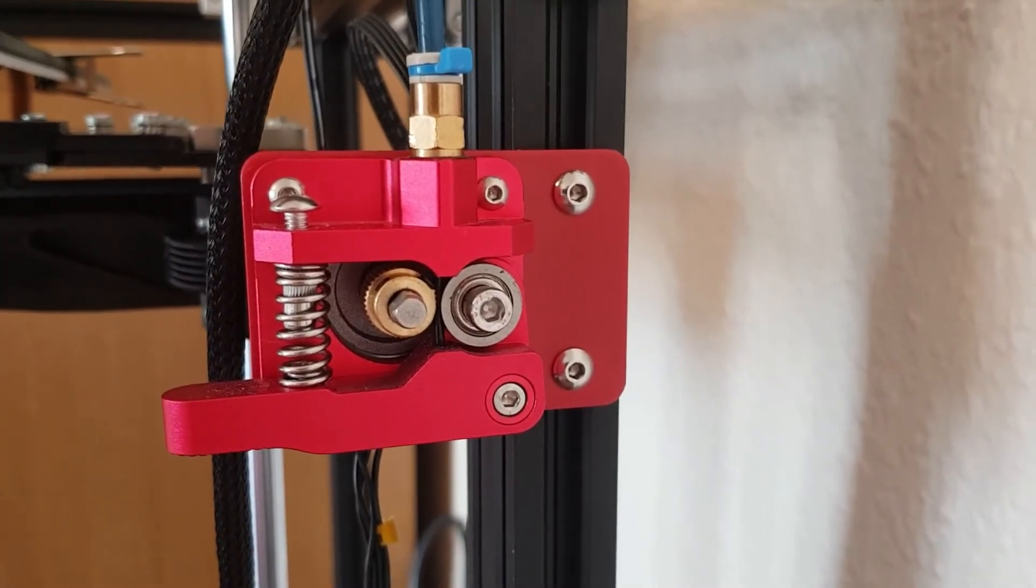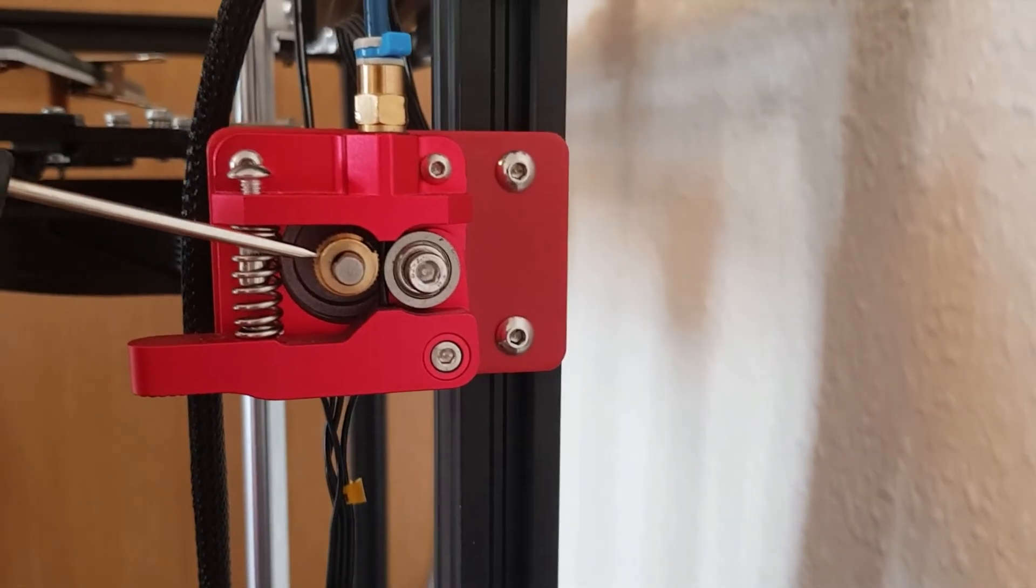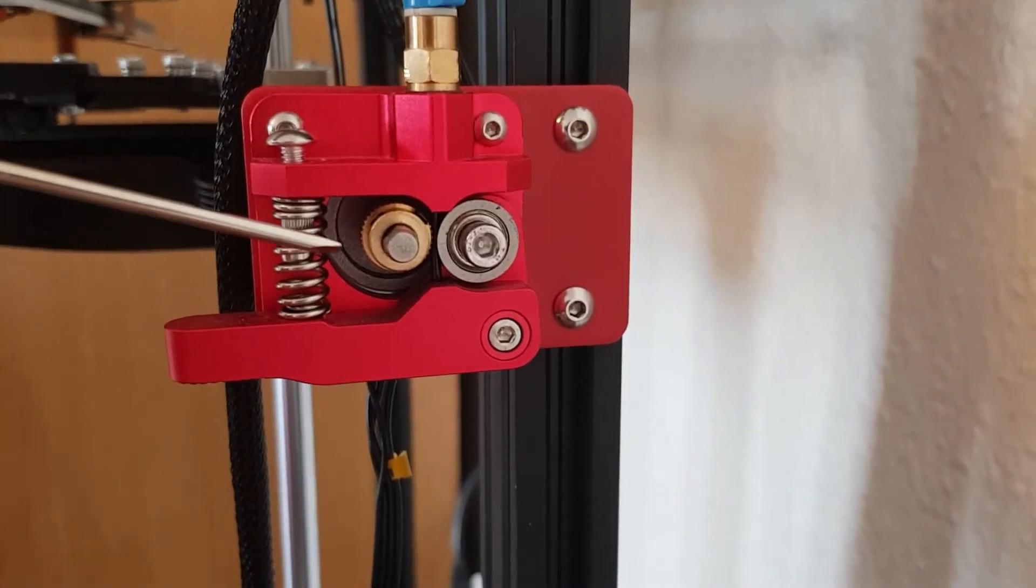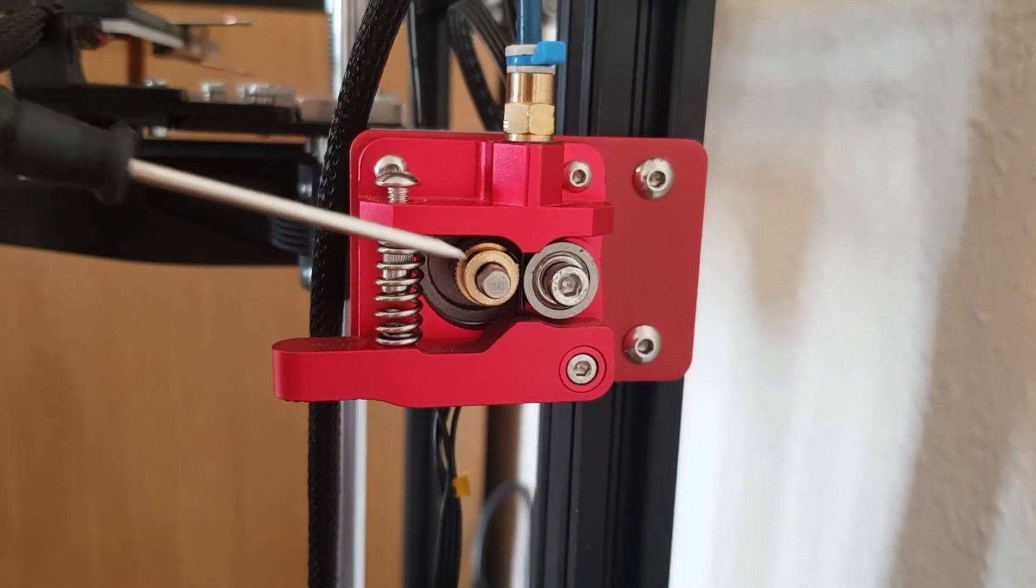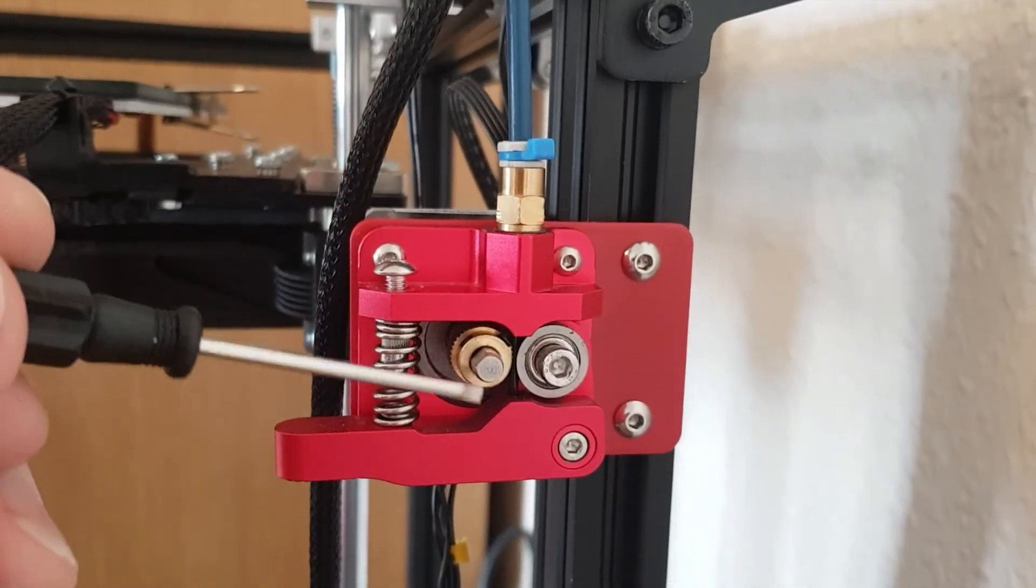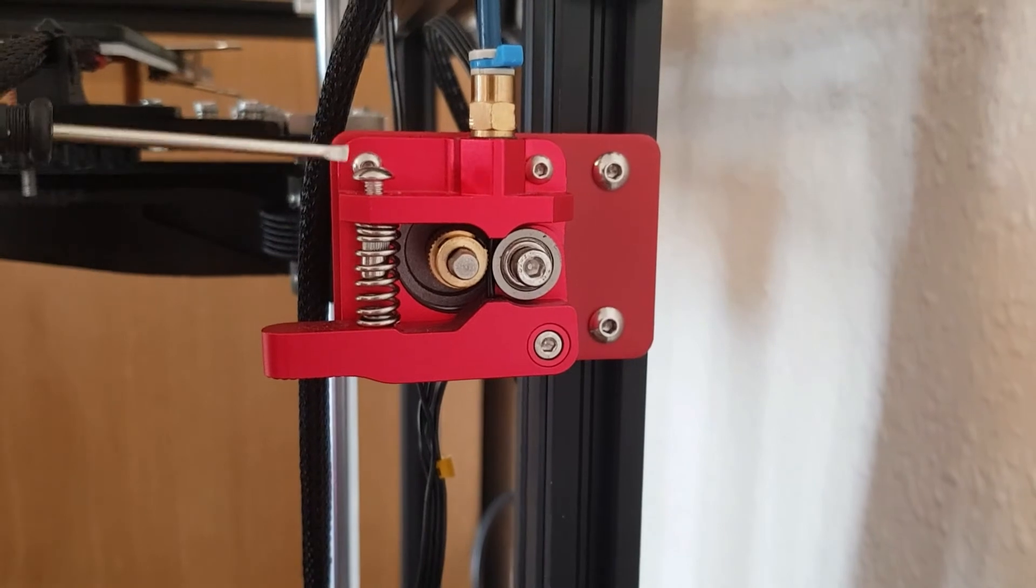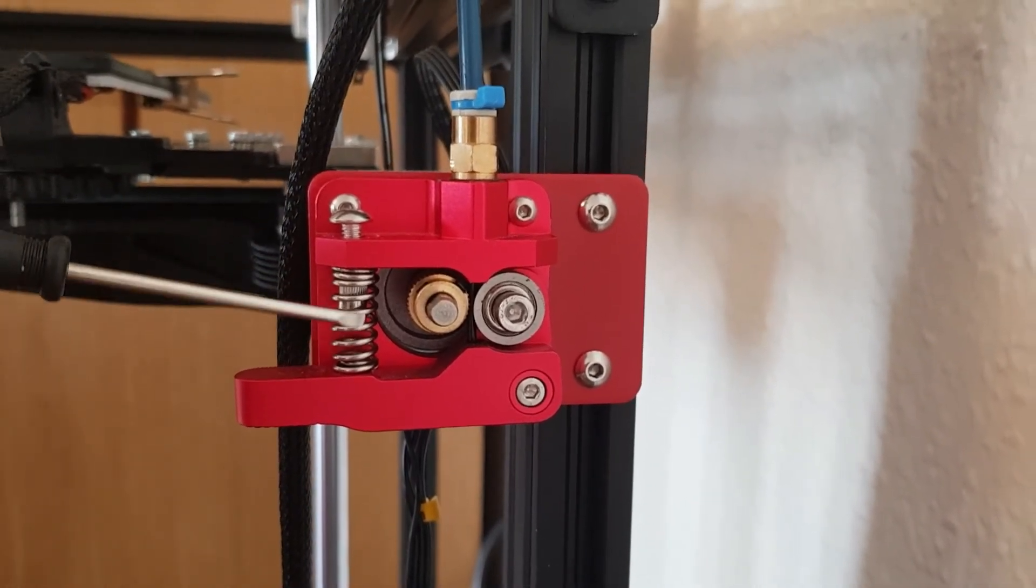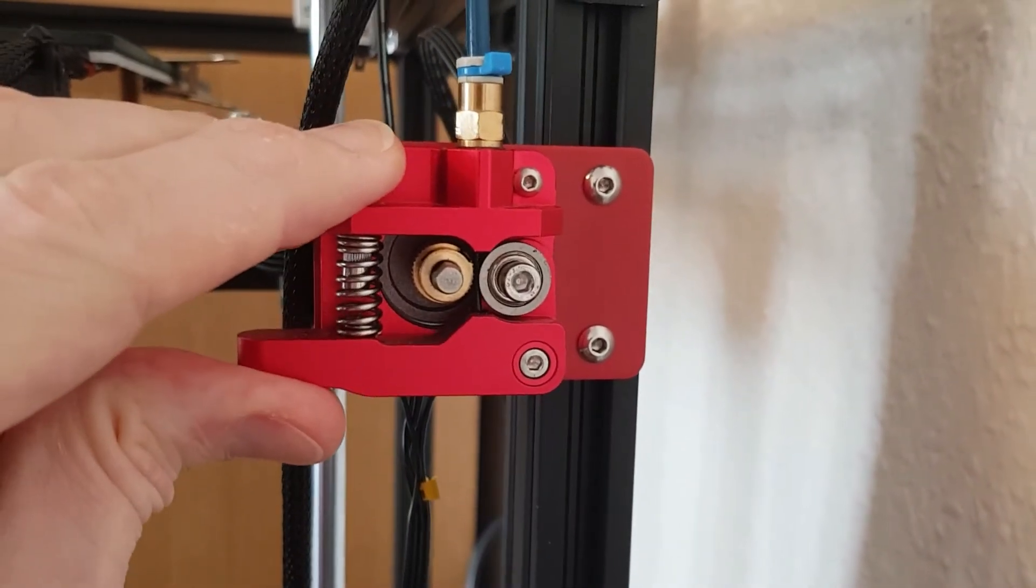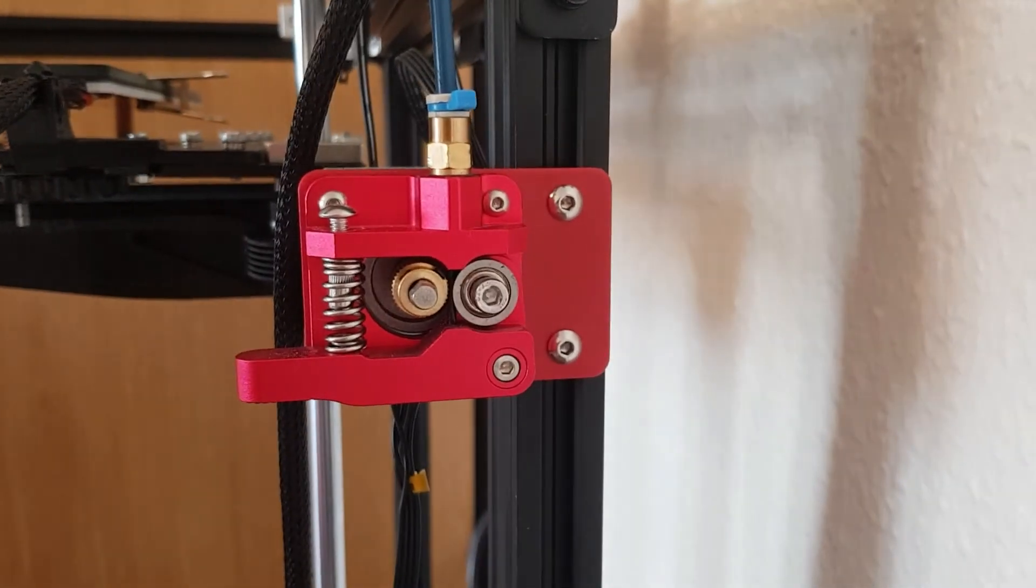So here's the extruder on my Ender 5 Pro and the problem I had was related to the tension of the stepper motor when it's pulling the filament through. And in this case with the PETG because it's a bit softer I found that if this spring was too tight it was forcing the cog to kind of bite into the PETG, deforming it to the point that as it was going through the tube to the hot end that it was causing some blockages. So what I found was in order to stop the problems during the prints was I actually had to slacken this screw off. It was actually tightened all the way down and it was compressing this spring. So just by turning it like this, now this seems to be giving it enough tension so that it can pull the filament through but doesn't deform it in a way that was causing the problems and that seemed to make quite a big difference.